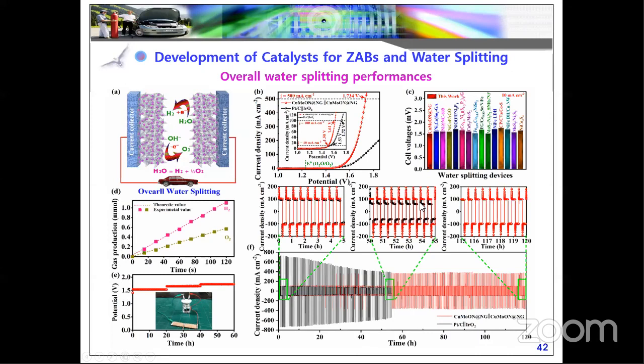From the studies, I also included the conventional catalyst. You can see the potential is reduced there, while in the case of our catalyst it is almost maintained. This is the HER side, here the OER side, and from the studies our catalyst is highly reversible. We also performed with different current densities, and the potential is more stable in the chronopotentiometric performances. Finally, our zinc air battery device was used to power the overall water splitting. When we connect our zinc air batteries in series connection, the water splitting performed very well.